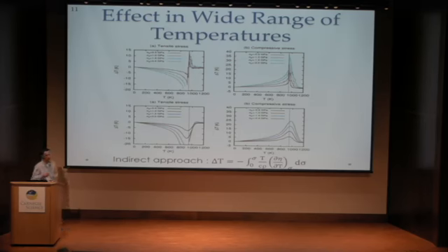This difference in amplitudes can be accounted for by the fact that the indirect approach doesn't account for the entropy associated with the first order transition that we have in this anti-ferroelectric. As I stated before, our direct method will account for that. So for the piezocaloric effect, the indirect method is not really applicable to give an appropriate estimate.